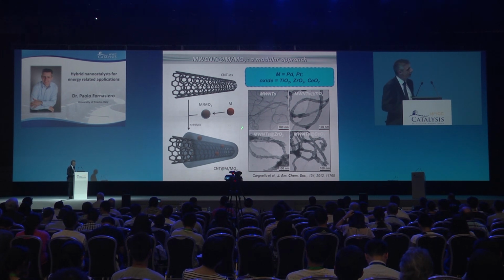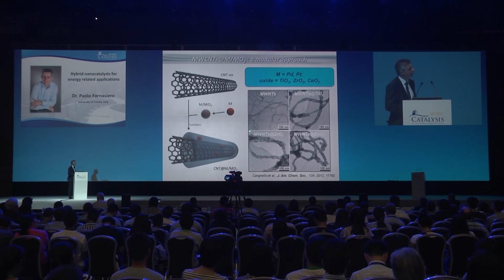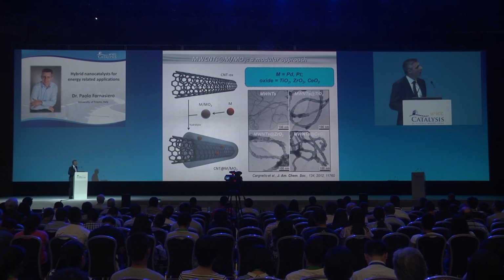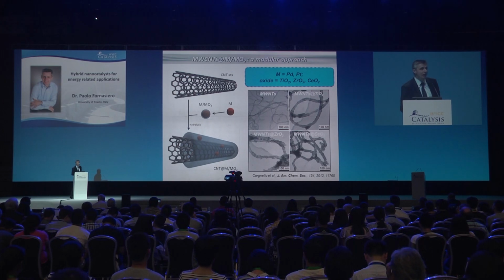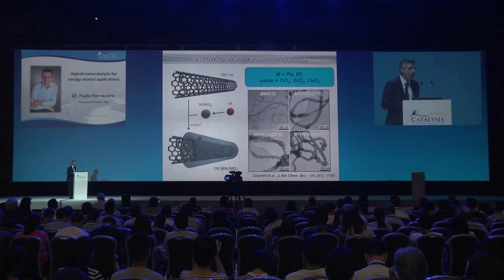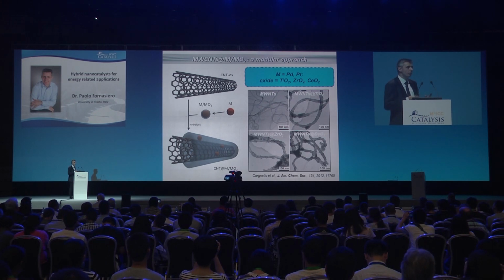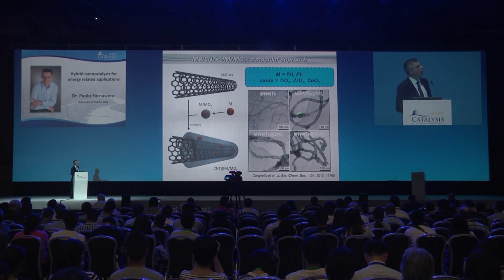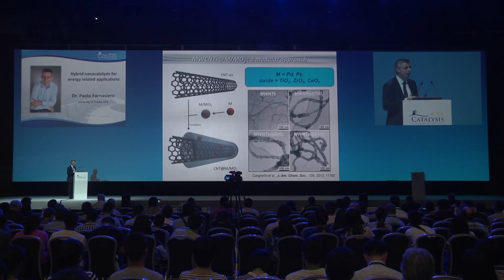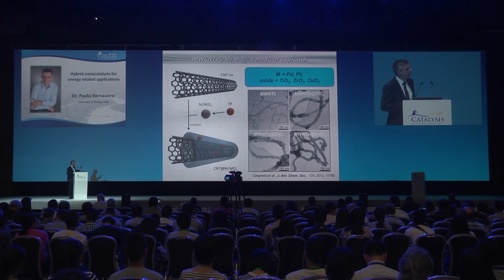the photocatalysis. So these are the first multi-walled carbon nanotubes that we used, and effectively we were able to cover them nicely with different types of oxide and metals. This is not a trivial, simple approach, as indeed you cannot just oxidize them, because you really want a tight contact between the components. You do not want naked nanotubes, naked carbon nanostructures, and oxide not in contact with the nanotubes.